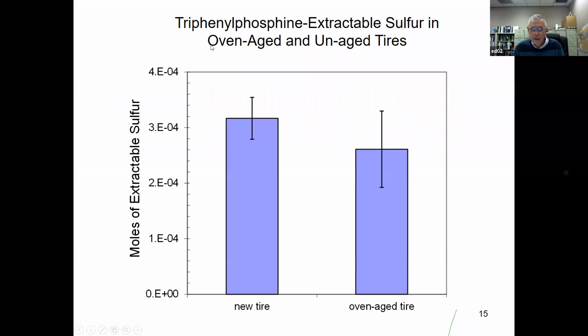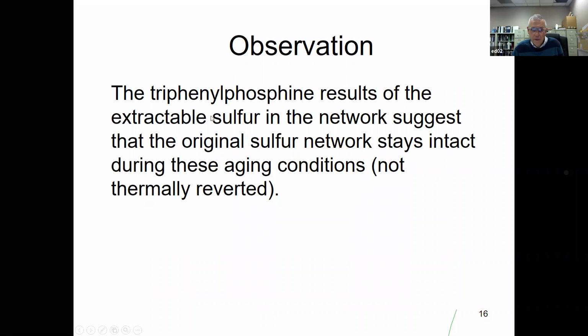And the next test, we're trying to determine the polysulfidics. This is triphenylphosphine extractable sulfur, which is a measure of the polysulfidics. The triphenylphosphine will extract sulfur from any sulfur linkage which has 3 or more sulfur atoms. This shows the data of the new tire and the oven aged tire, and we say they're not significantly different in this test. So we say the triphenylphosphine extractable sulfur measurement suggests that the original sulfur network stays intact during these aging conditions. No thermal reversion. No evidence of thermal reversion.